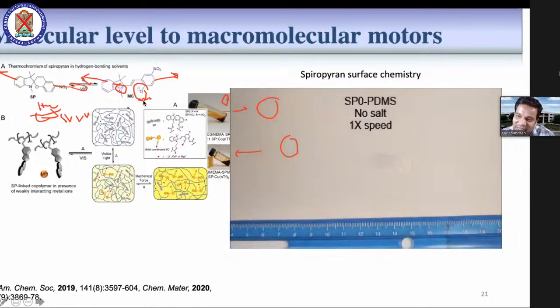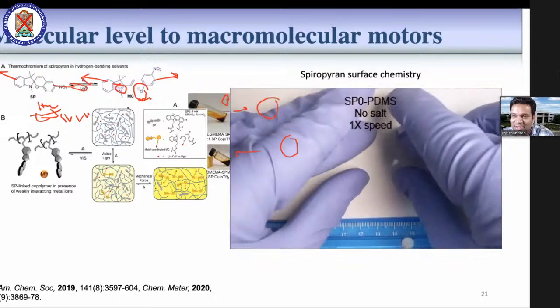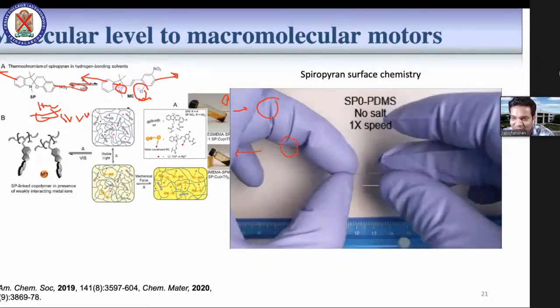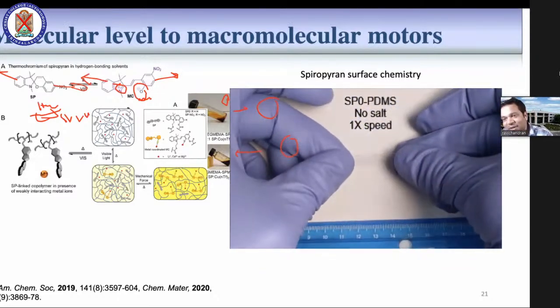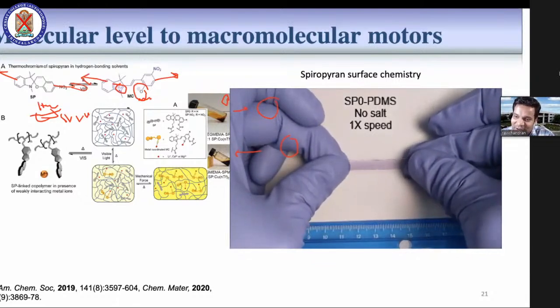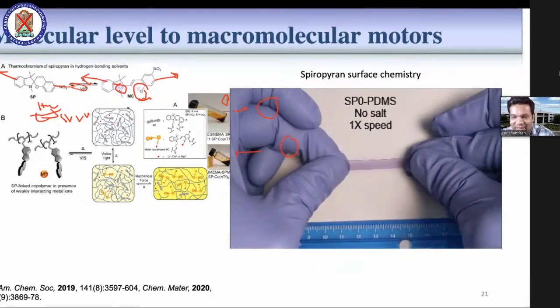And after a few seconds, it reverses back. The reverse process can be tuned depending on the concentration of the spiropyran. If you want more concentration of spiropyran, it takes more time. But if you load a low concentration of the spiropyran, it happens in minutes to seconds.